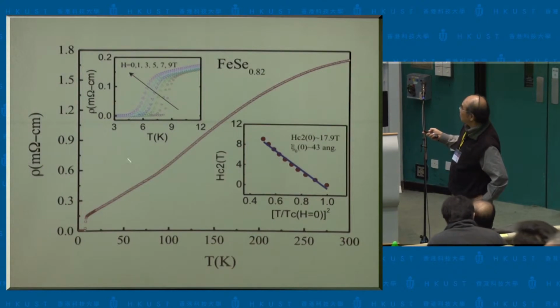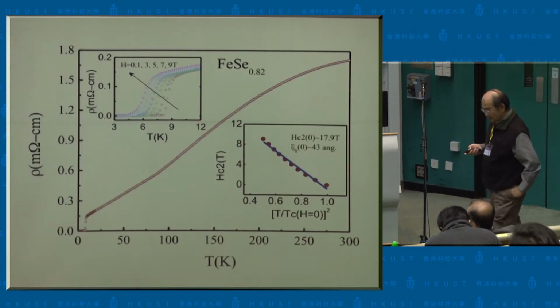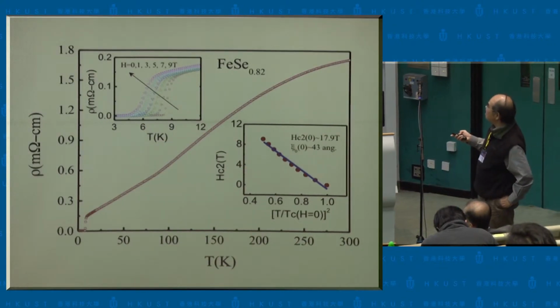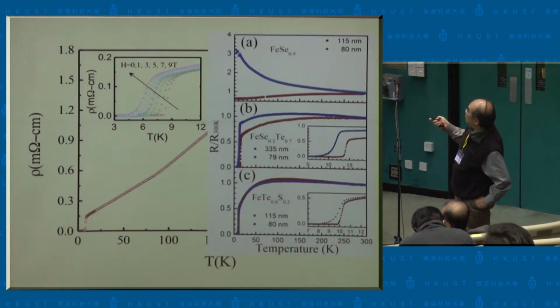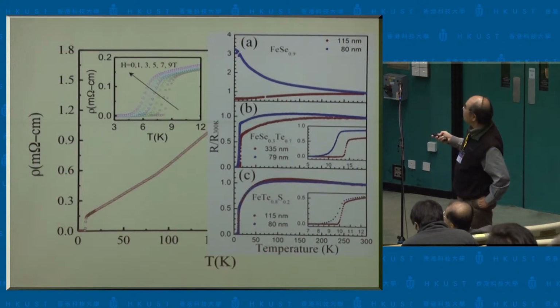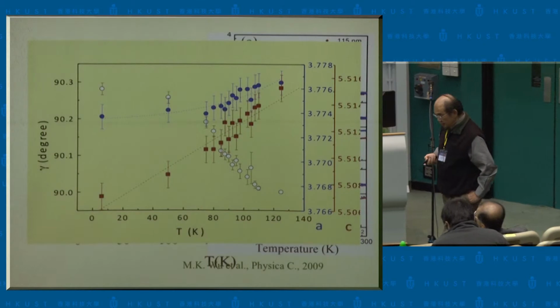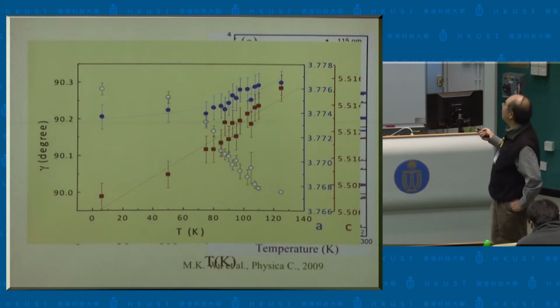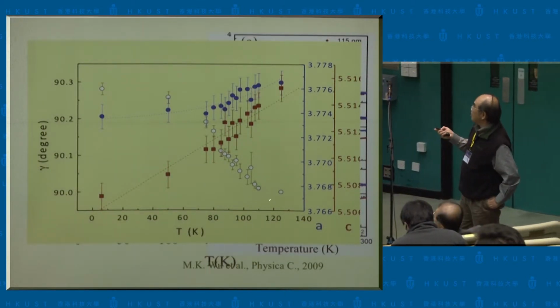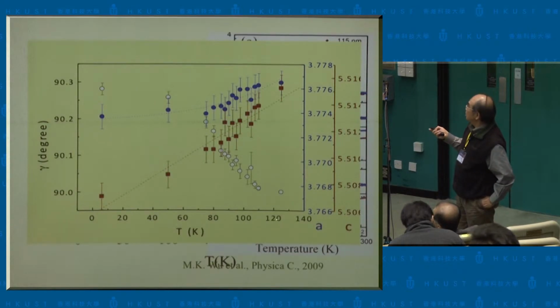Let me first talk about this 90 Kelvin feature, something around 90 Kelvin, which was identified the first time we discovered this material. By the way, I want to mention that not only this kind of bulk, but also all the nanowires that show superconductivity indeed show this kind of interesting behavior.